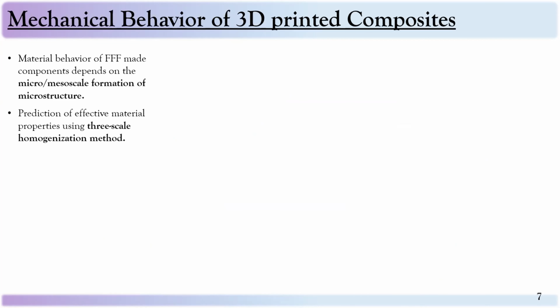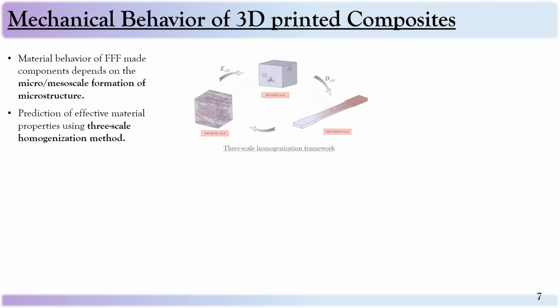So, okay, let's go back to see how we obtain effective properties of 3D printed composite parts, and I'll briefly summarize it. Here we perform a 3-scale homogenization approach to obtain effective material properties for ABS and carbon fiber reinforced ABS material. The first scale is the micro scale, which consists of short carbon fibers and ABS matrix domain. And then the mesoscale, which some of our researchers talked about, is its interbead shapes with interbead voids. This is created during the layer by layer deposition process.